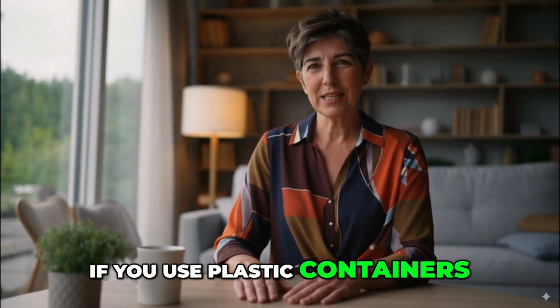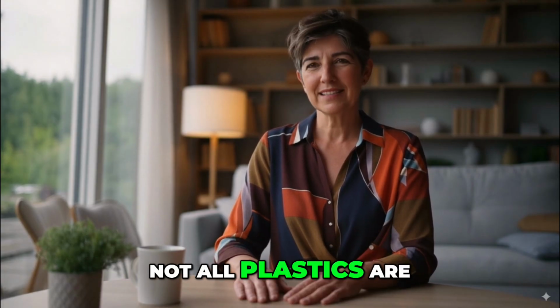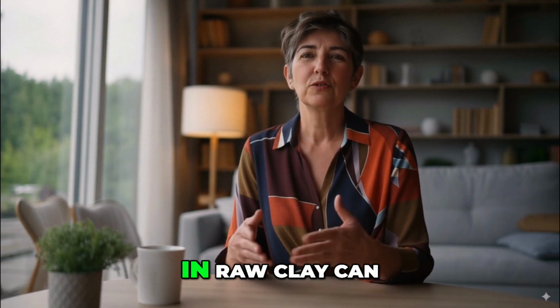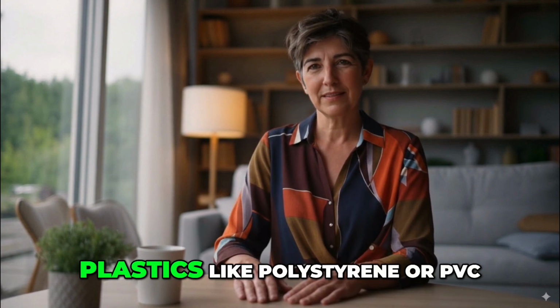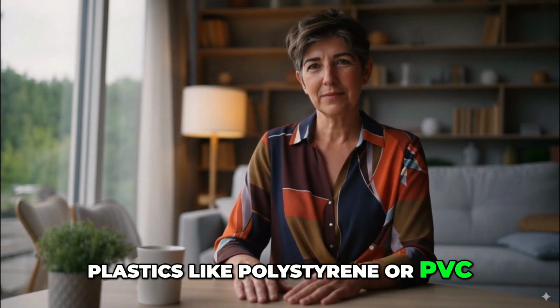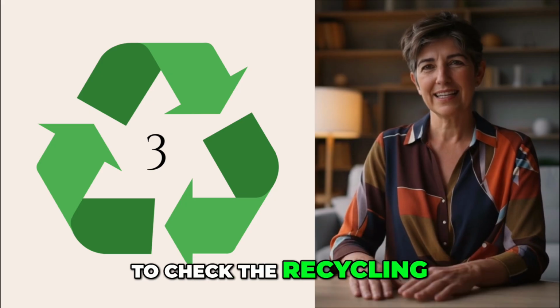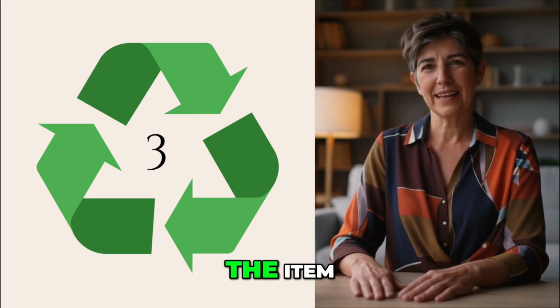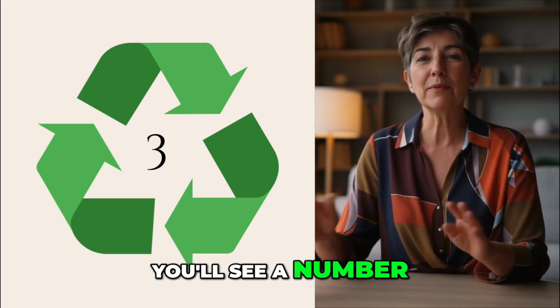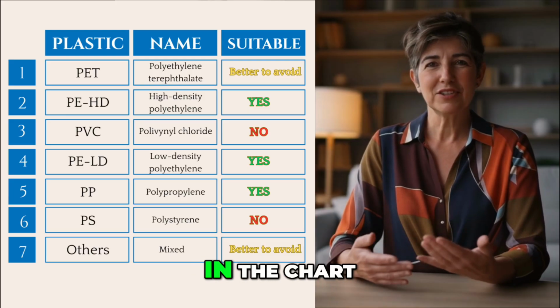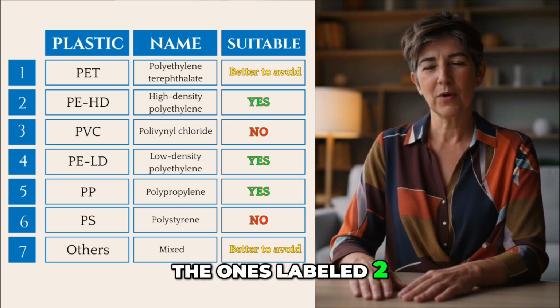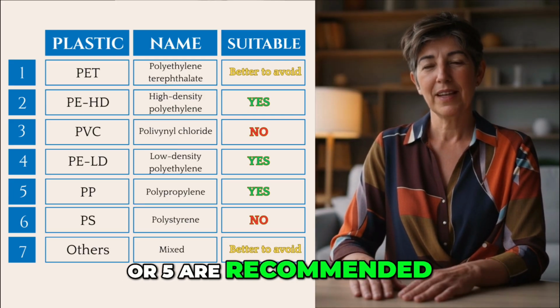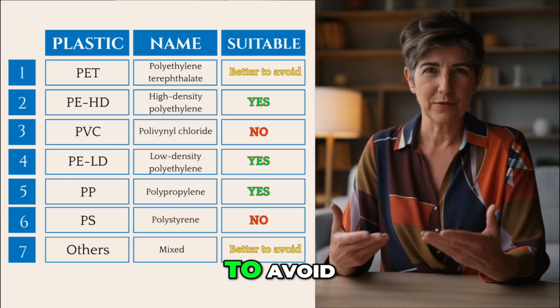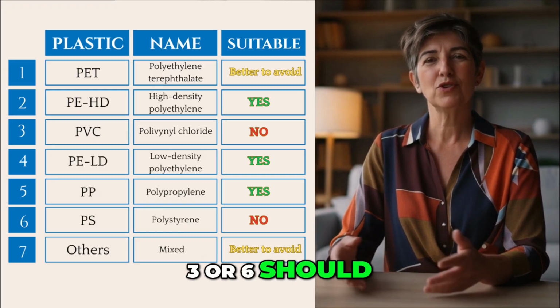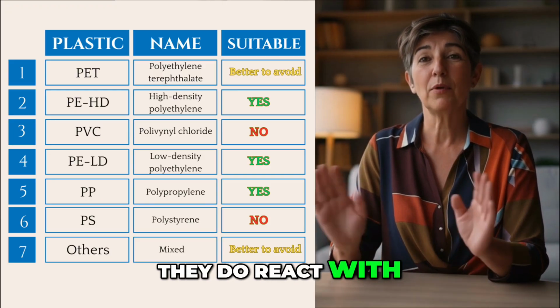If you use plastic containers, keep in mind that not all plastics are advisable, because the plasticizer in raw clay can soften or dissolve some plastics, like polystyrene or PVC. The easiest way is to check the recycling triangle symbol on the bottom or back of the item. Inside the triangle, you'll see a number from 1 to 7. As we can see in the chart, the ones labeled 2, 4, or 5 are recommended. The ones labeled 1 or 7 are better to avoid, and the ones labeled 3 or 6 should not be used, because they do react with polymer clay.